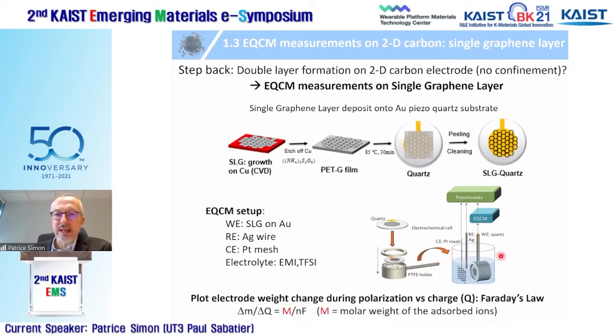And what is interesting, exactly like your QCM, is that your quartz has a resonance frequency, and as long as the weight of your electrode changes, you will end up with a change in the resonance frequency. And you can convert the change of frequency into a mass, a weight change. And by using Faraday's law, you can calculate the charge passed during your electrochemical process.